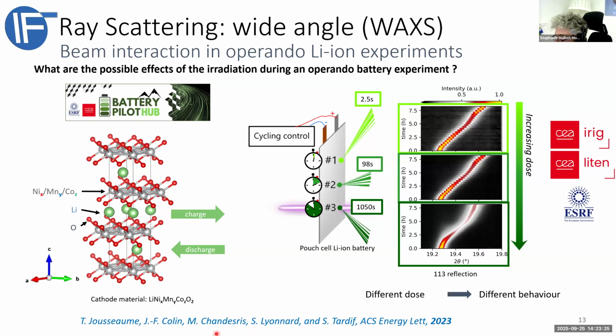So in this nice paper, the colleagues have recommended to use this kind of dose quantitatively on these core-shell geometry samples, to avoid having data which are not really reliable. So clearly, the idea was to shorten the slits and to reduce the beam intensity, in order to be sure to measure something which is reliable.